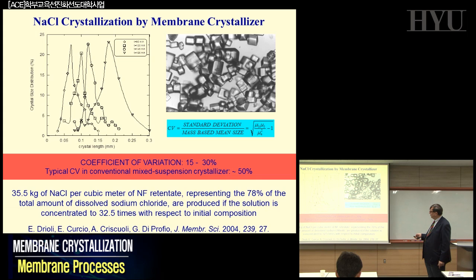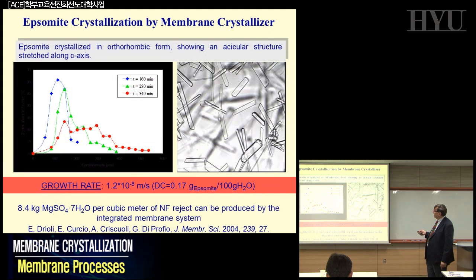That means the deviation of the size of the crystal compared to the average. Normally in most systems this is about 50% at best, when you have a very good crystallizer. With membrane systems, you have a variation of about 15%, at most 30%. So the crystal size distribution is much sharper and more regular than the one you normally have in traditional systems. This 50 is becoming 15 when you are smart, or at most 30%. And that is one of these quite interesting results for which everybody is now spending $70 million, in your case here in Korea, for having this kind of crystals.